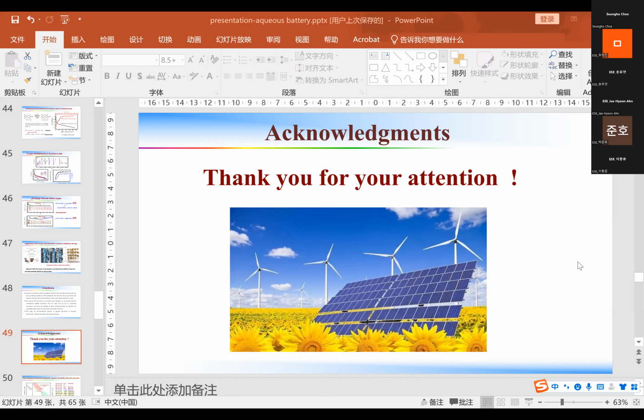So one student asks you about the future of aqueous zinc batteries. Aqueous zinc batteries, yeah. I think aqueous zinc batteries are also a very promising system for aqueous batteries. We are also working recently on zinc-based aqueous batteries. The specific energy is much higher than our systems. We use intercalation reactions because we use zinc as the negative electrode material. So we think these batteries can have an energy density over 60 watt-hours per kilogram. It's possible for practical batteries to get 60 watt-hours per kilogram, which is much higher than our intercalation systems, about 30